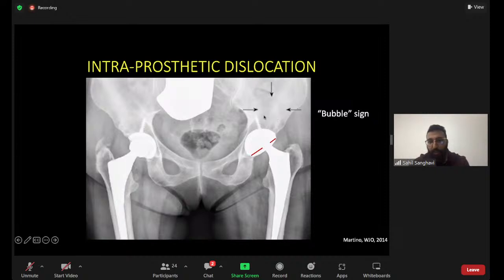Which is why, if you see closely, this is known as the bubble sign. The black arrows here show you that the radiolucent polyethylene is lying outside the hip. And if you look closely at the X-ray, the head or the neck is in an eccentric position. There is more space medially as compared to superolaterally, as demonstrated by the red lines. So this is a unique complication of intraprosthetic dislocation. So again, for dual mobility dislocations, it's better to go in for an open reduction.